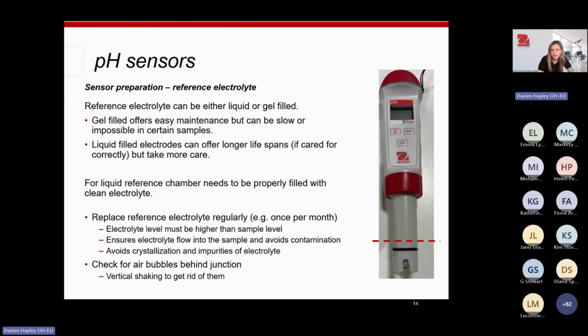For the liquid reference, the chamber needs to be properly filled with clean electrolyte. I'm not sure if you've got any users on today that have liquid filled reference electrodes, but if you do, you have to replace the electrolyte once a month. Again, don't top it up completely. Release everything that's in there, give it a rinse, and then replace it with fresh reference electrolyte regularly. The electrolyte level must be higher than the level of the sample. There is another picture on one of the slides which I'll show you. That ensures that the electrolyte flows into the sample and stops any contamination. It avoids crystallization and impurities of the electrolyte as well. Also check for air bubbles behind the junction. A little bit of shaking side to side would generally get rid of any air bubbles in the reference.